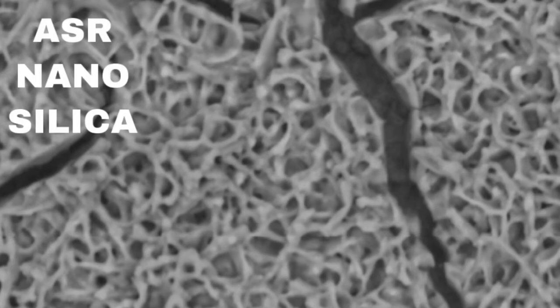Jump into my PhD — I think it's chapter five or six that goes into it. There are hundreds of pictures we took, not only of the top surface, but also of different sites at different magnifications. One of the other things we see from the nanosilica is not just that we're using up that byproduct calcium hydroxide to create more of that backbone of concrete strength, but it's also those alkalis — the sodiums and the potassiums that contribute to alkali silica reaction. We find that they're bound more in the hydrated cement matrix, not only because we're using up that pore solution, but also because we're densifying the hydrated cement matrix and ultimately chemically binding these alkalis that would normally transport through the percolation or pore connectivity of our hydrated cement matrix.